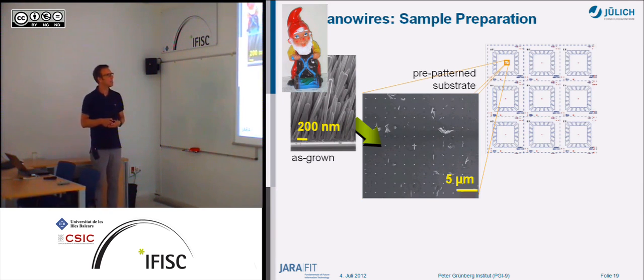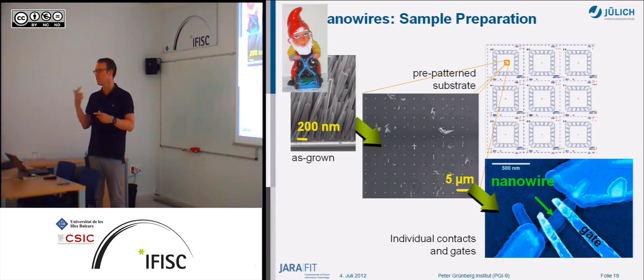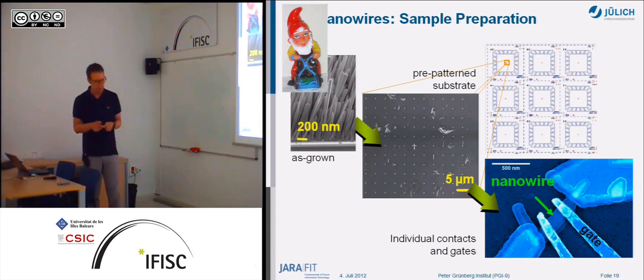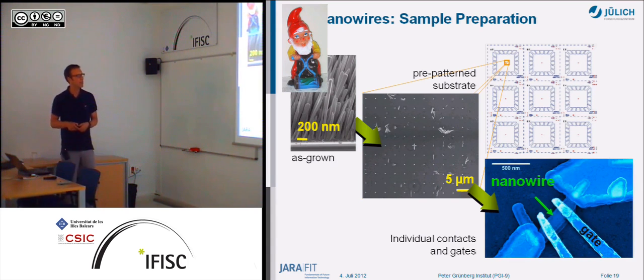You put the nanowires here randomly on the surface, and the next task is to find these nanowires to get contacts on them. So you do it in that way that you do electron beam microscopy. You take a picture of the sample, and then you see where the alignment markers are, you see where the nanowires are. This helps you to design, by electron beam lithography, the contacts so that later on the structure looks like this.